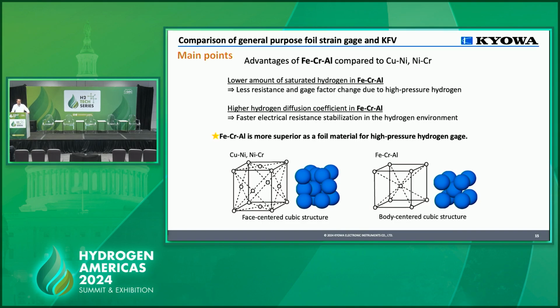This performance difference is due to the advantages of iron chromium alloy, which is used for the sensing element of the KFV strain gauges. Point number one is a lower amount of saturated hydrogen in iron chromium alloy. It contributes to less electrical resistance and gauge factor change due to high pressure hydrogen. Advantage number two is a higher hydrogen diffusion coefficient in iron chromium alloy. It contributes to faster electrical resistance stabilization in the hydrogen environment.